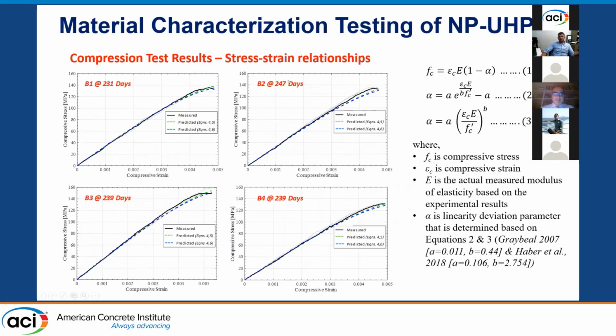Of course, this project was happening last year, right around the COVID shutdown. So you will see a lot of weird times here for testing. It all depended on when we were allowed to go back to use the lab and so on. So there are some results that we were able to get at standard times, like 28 days or so. Some specimens, we couldn't test at 28 days and we had to wait until we were back in the labs. So for the compression stress strain ones, we were not able to test these until almost 240 days or so.